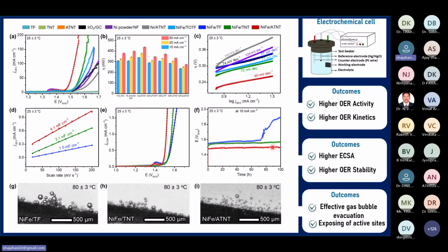ATNT based and TNT based electrodes are both superhydrophilic in nature, as we discussed previously. So these two maintain good stability compared to the hydrophobic based one. The hydrophobic based one only showed 72 hours, but these two have shown 100 hours. So what is the reason?